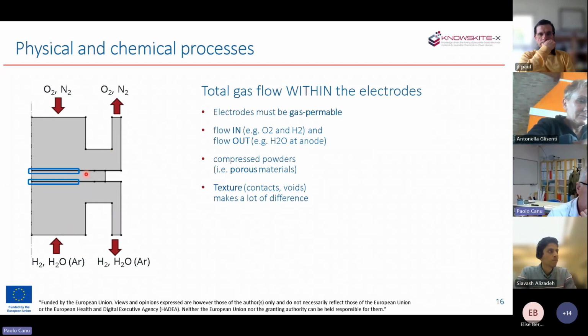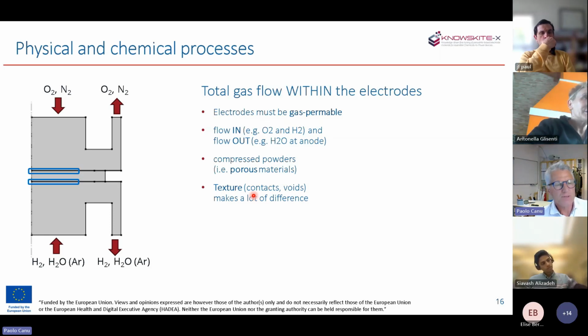There's also a process of gases moving within the electrode because they are porous. That means that the electrodes must be permeable to gases, so they must allow some empty space for the gases to permeate through the texture of the electrode, that are essentially made by compressed powders. So they indeed allow for some room, even very narrow, let's say, pores, for the gases to flow. It's extremely relevant to describe the flow within the electrode, the texture, that is how powders have been packed together. So the amount of empty space and the tortuosity of these pores.